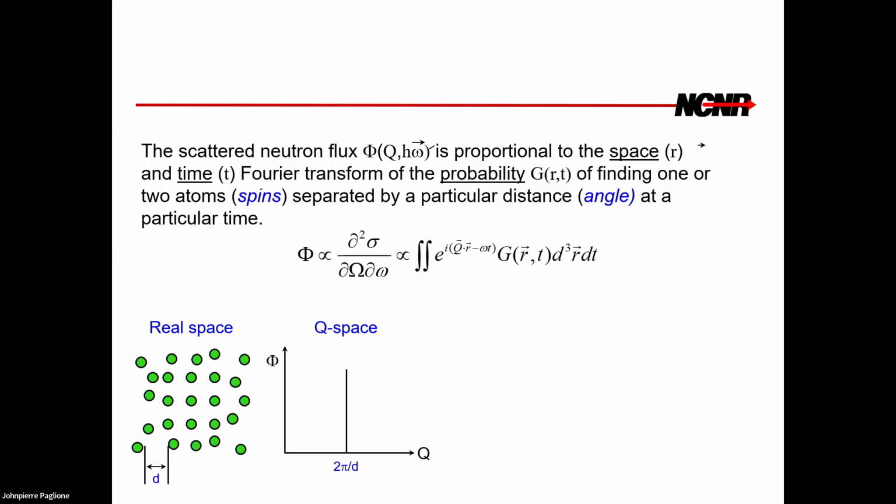For example, showing here structural disorder, but you could have a periodic array and then have magnetic disorder where the spins are disordered in orientation. And what will happen is you'll get a correlation length over which the atoms look like they're ordered, but then you drop that, and what you'll get instead of a delta function is a width of that peak.